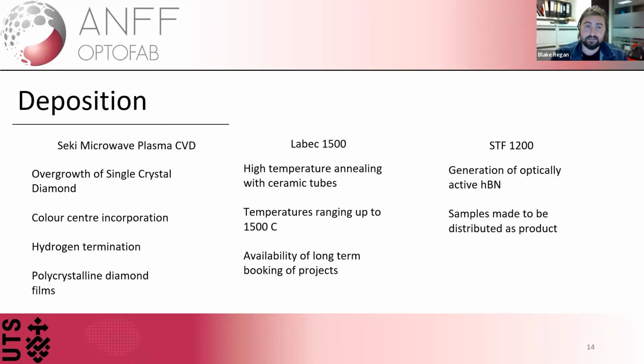crystal diamond. Now, what this means is that we can take a small amount of diamond that is already predetermined. My particular area was in diamond membranes, but we can also do bulk diamond and nano diamonds, and we can grow this material outwards to make it larger. Now, you could do this for a number of reasons. The first one being is either A, you want fresh diamond.